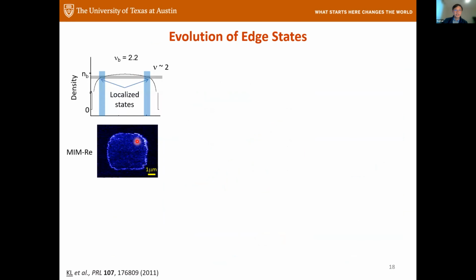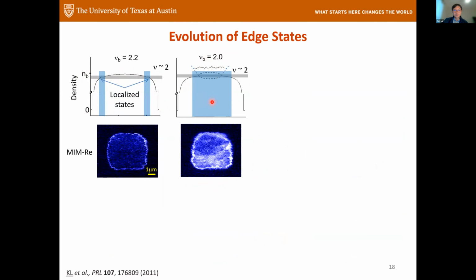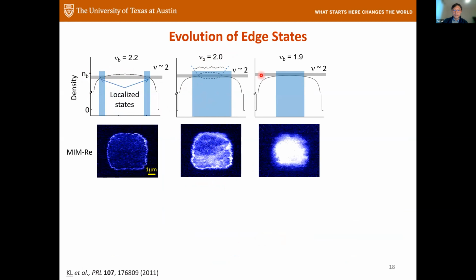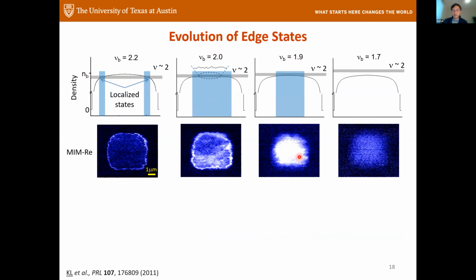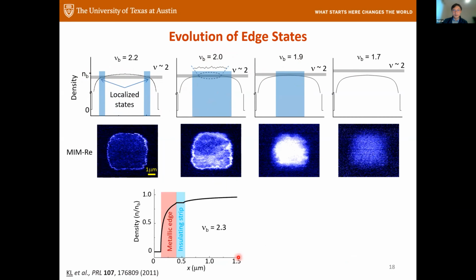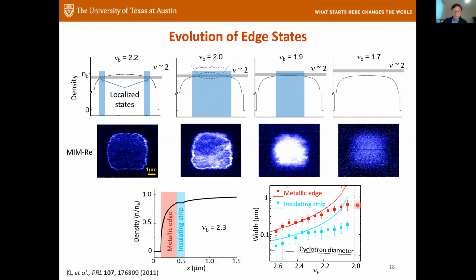And so the physics is fairly straightforward. You have this density profile that cuts through the localized states. At filling 2, you have a lot of lossy states in the middle. As the filling factor gets smaller and smaller, eventually the material becomes conductive again. We can actually quantify the size of the metallic strip and the insulating strip from our images and plot them as a function of filling factor and compare it with the theory. Again, if you're interested, this is mostly in this PRL paper quite a while ago.